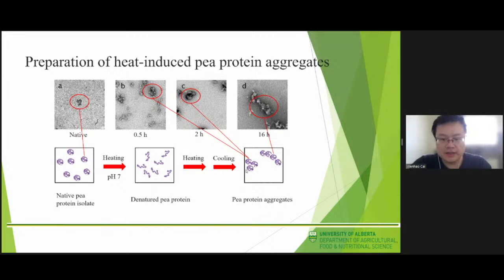In Figure A, no intense aggregation was observed for untreated pea protein. As shown in Figure B and C, soluble aggregates prepared by half an hour and 2 hour heating treatment appeared as non-spherical particles with size of 50 to 100 nanometers, and 2 hour aggregates showed a slightly larger size.